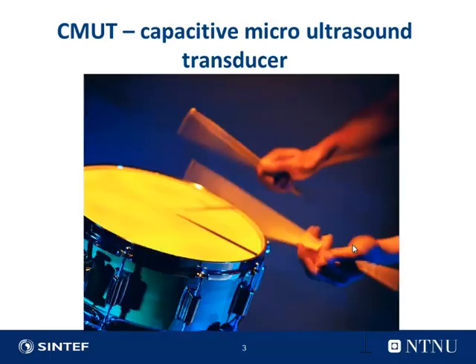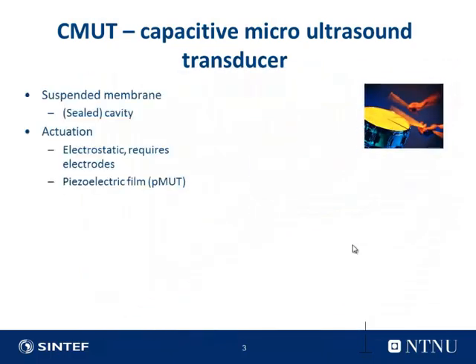So here's where the CMUT comes in. A CMUT is basically a drum that is actuated by electrostatic forces. So you need some kind of suspended membrane, preferably with a sealed cavity if it's to be used outside of air. And you also need, of course, the electrodes for actuation. You can choose here between MEMS fabrication with bulk and surface micromachining. We believe that bulk micromachining, at least for these frequencies, is the best because you can use high quality materials and you get better material properties.